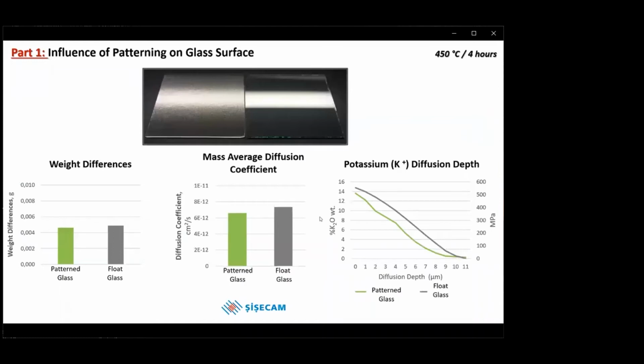Let's continue with the first part. This slide shows the patterned and float glasses which were chemically tempered at 450 degrees for 4 hours, the weight difference before and after the chemical tempering process, and the diffusion coefficients and depth of potassium ions in the glass after the process. It's seen that the highest weight difference value, the highest diffusion coefficient values, and the highest potassium diffusion depth values were obtained for the 2 mm float glass sample.